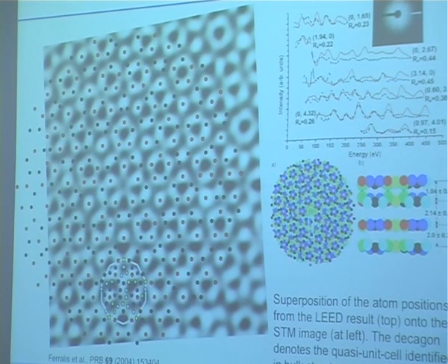An interesting question is, for example, if you have a quasicrystal, what does the surface of a quasicrystal look like? Is it the same as in the bulk, or does it reconstruct? Is it different? A lot of work has been done on quasicrystal surfaces, and fortunately, quasicrystal surfaces terminate like in the bulk. There are slight relaxations, but essentially the bulk structure exists. And this is also quite helpful if you want to determine a quasicrystal structure. Here is one example, again aluminium, cobalt, nickel, and such a model cluster fits quite nicely.